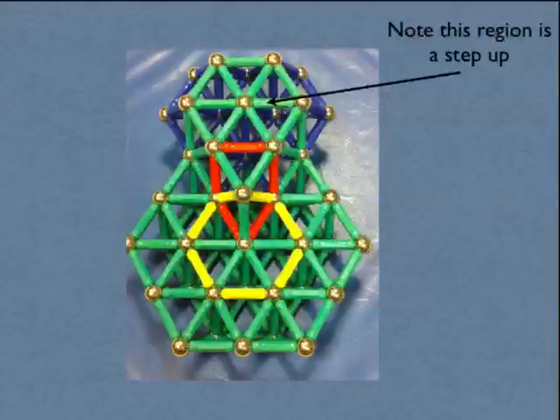This is something I built from these Chinese Lego things with magnets and rods here. This is a 7, and this is a 5. You guys all see that? This guy is a plane here, and when I put these together, just like I showed you here, if I let myself relax from being two-dimensional, I can make something with these topological defects in it, which doesn't have any strain energy. If I do the same thing with 2 of them together, I get something here which is a dislocation, but there's no strain because all of these rods have exactly the same length.